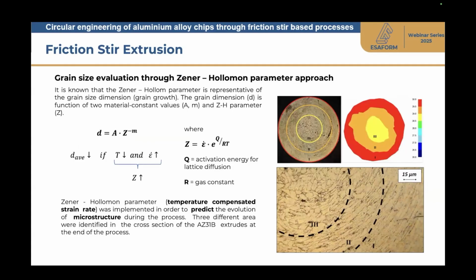And in this case, it was possible also to relate somehow the average grain size in the wire section, in the extruded part section, with the Zener-Holloman parameter of the material during the process. Zener-Holloman is the temperature-compensated strain rate, and it was implemented and calculated in order somehow to predict the evolution of microstructure during the process.